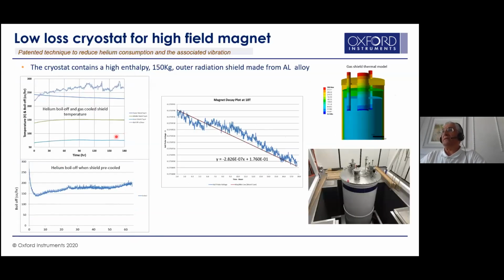With this low loss system, you could see how within 2 days the temperature doesn't exceed certain values, with helium boil off within the shield pre-cooled specification. More importantly is high persistence. It gets into the desired persistence value, the decay value, within less than 15, 16 hours.